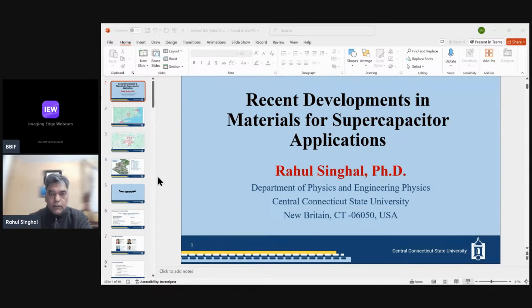We want to see the effect of multi-wall carbon nanotubes on the electrochemical performance of MnO2 for supercapacitor applications. We are using manganese oxide because it is naturally abundant, has low environmental toxicity, and is cost effective. The carbon material serves as a highly conductive and stable current collector, and its interconnected holes are beneficial for ion diffusion. The improvement of the active materials mainly involves high reversible capacitance, structure stability, and rapid cation diffusion at high charge discharge rates.